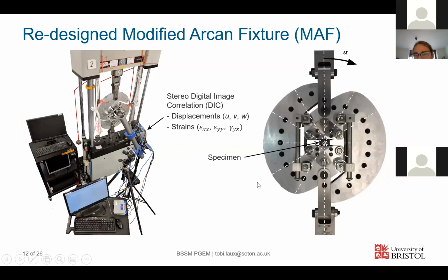So this is this rig, which is based on a similar rig, but I basically redesigned this for my PhD to enable testing of carbon epoxy multidirectional laminates. And how it works: you take this rig with the many holes, and by choosing the loading hole pair, if you put it in a standard test machine, you induce different load cases.